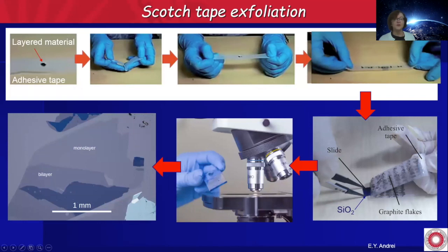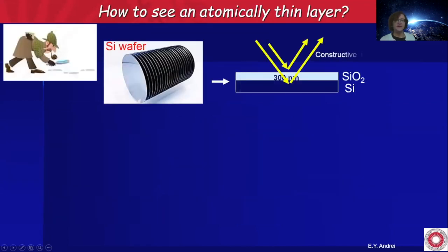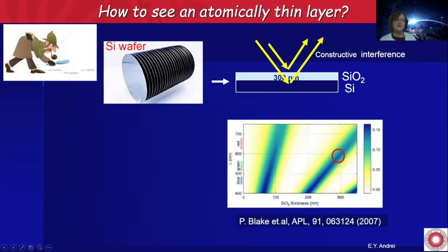This is a silicon wafer. And by the faintness of the shadow, you can identify a monolayer or a bilayer or more layers. Then you can actually go and measure it with the atomic force microscope and realize that you indeed have a one atom thick layer of graphite. Now, this discovery was completely serendipitous.